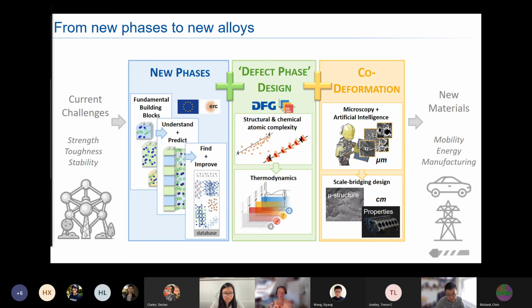And so we think that gives you a starting point to put defects into competition, because again, even if you just use a single phase alloy, you have your alloying species in there, and it has to decide whether it wants to go to a twin boundary or an edge dislocation, right? And that affects the remaining alloying content that you have for further segregation. So this is how we're going to try and put the two together, to use the chemical potential, and then we can also have different defects in competition later.